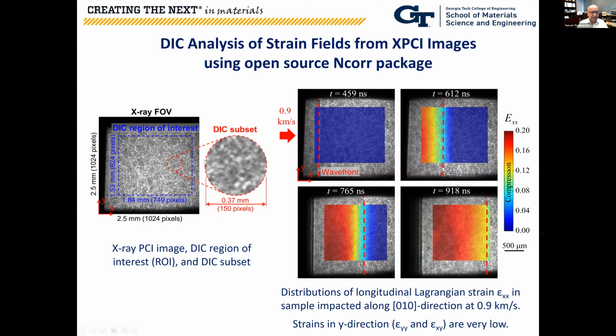So if this is a region of interest, these 4 figures here are showing you the evolution of the normal strain epsilon xx. The color contours here are indicating the magnitude of the strain. The blue is very low, and the red is strain up to 20%.